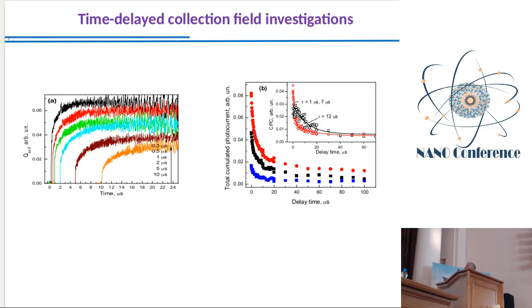And here you see the dependence of this extracted charge on the delay time, and as you can see, initially the extracted charge drops very rapidly during something like 20 microseconds, but it means that still charge carriers survive something like more than 20 microseconds. And later on, we have a long tail lasting for more than 100 microseconds. So it means that some charge carriers may survive quite long. They do not recombine during this 100 microseconds.